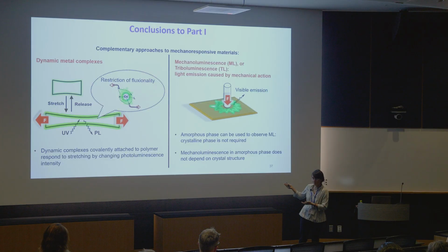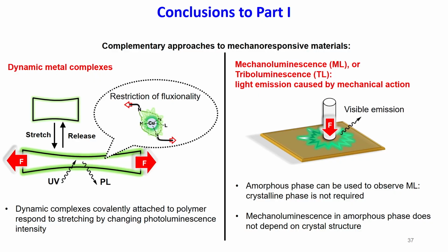Now, the complementary approach would not require an external light source. There, we would use a mechanical activation, for example, rubbing, twisting, and contact separation to emit light directly through the mechanical activation. And the interesting discovery here, I believe, was that we found that actually it works very well in the amorphous state, and the crystalline phase is not required to see it.